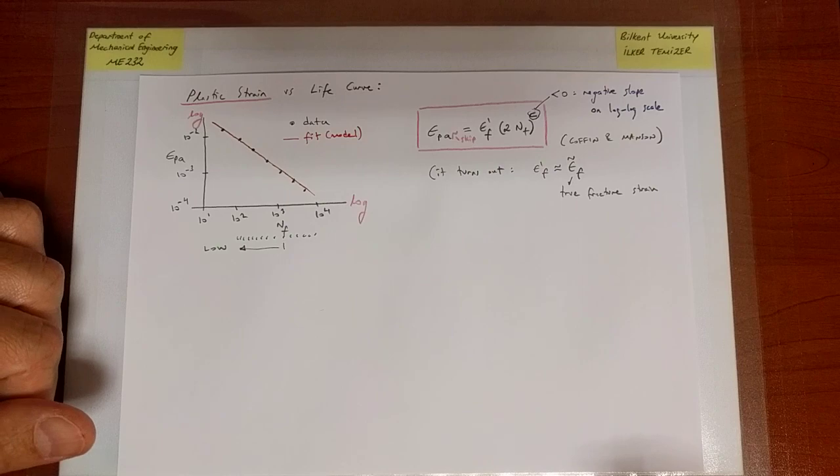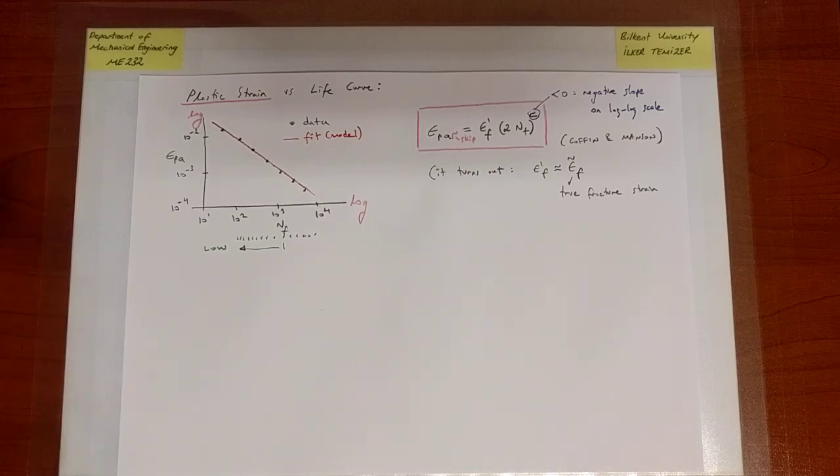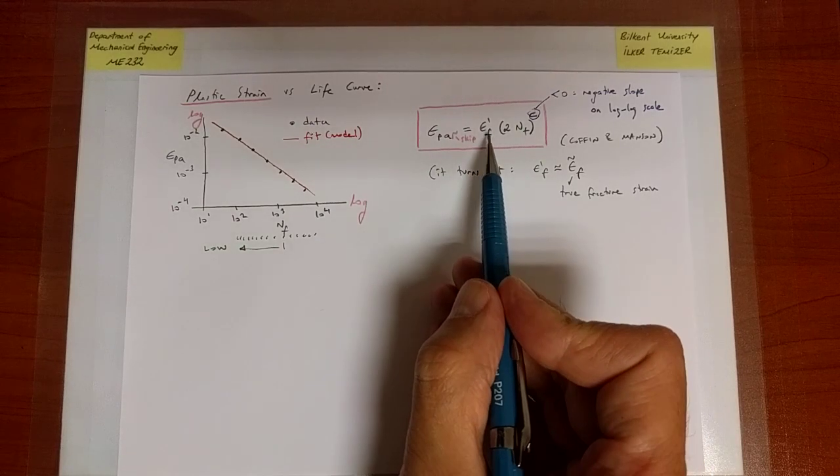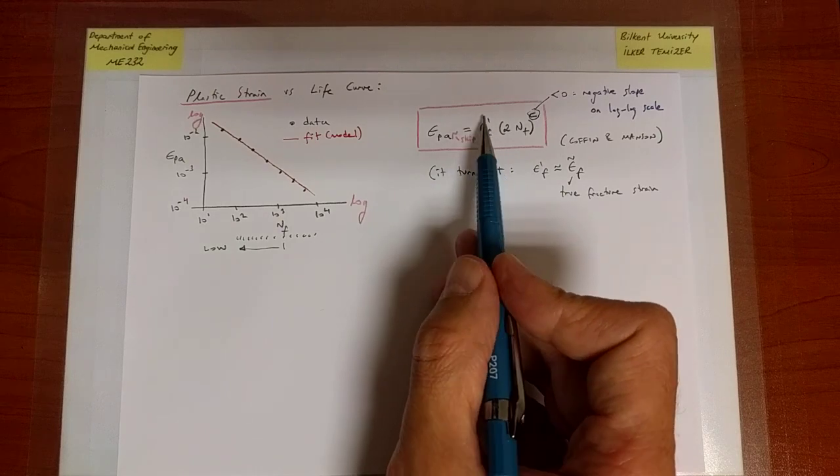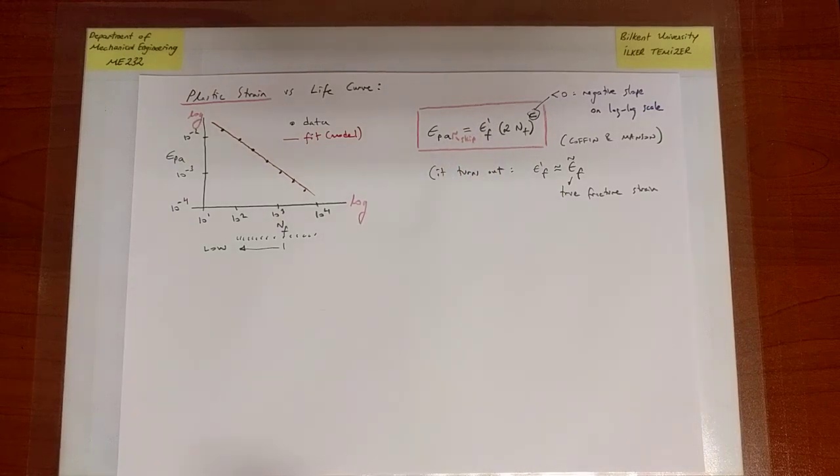Okay, so epsilon'_f, if we don't know exactly what it is, we can approximate it as being the true fracture strain. Of course, there's ample experimental data that's going to tell us what epsilon'_f should be for strain-based fatigue applications.